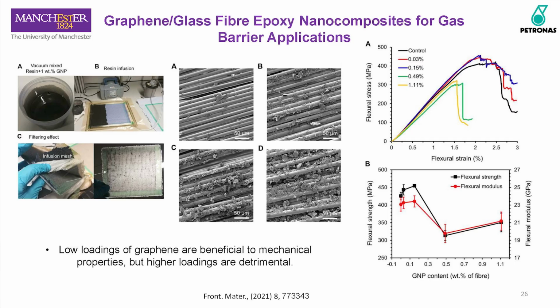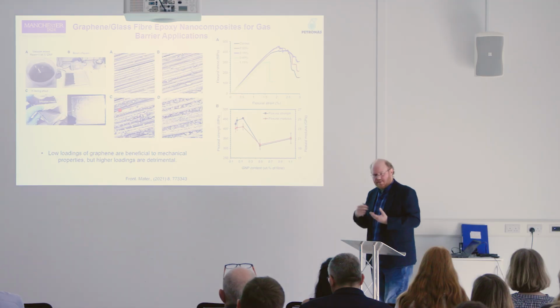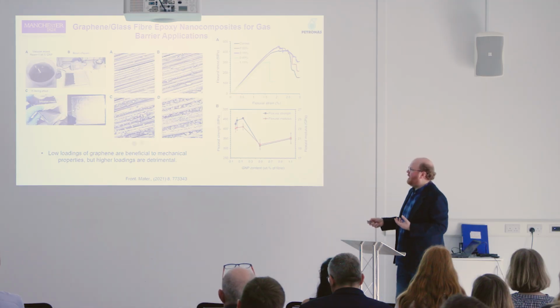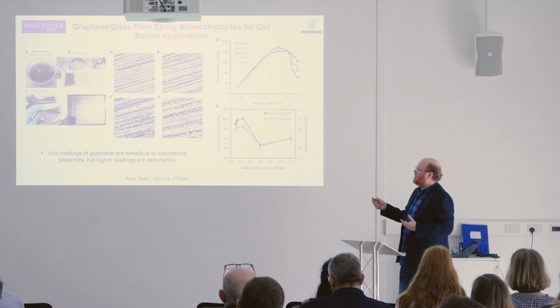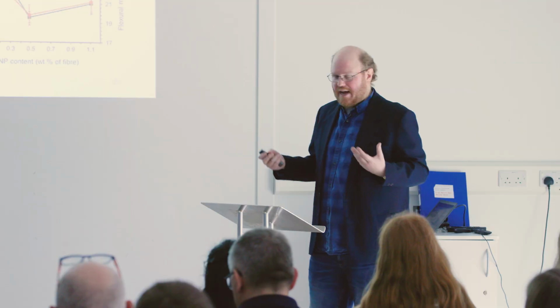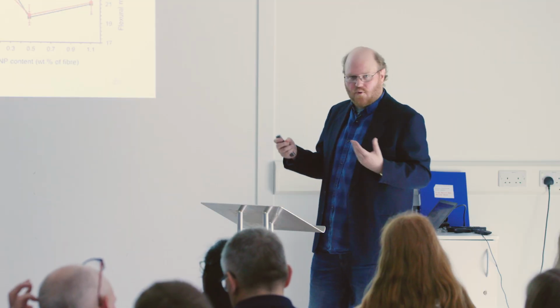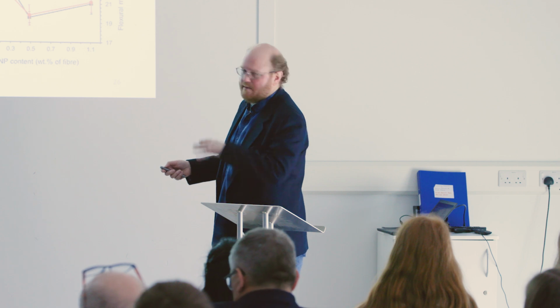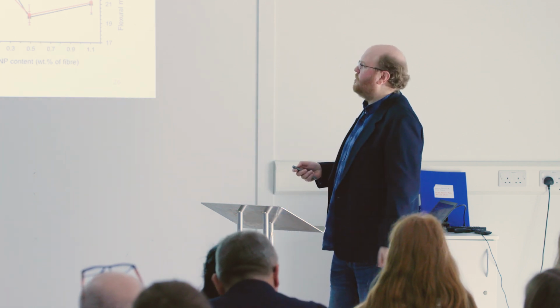This was looking at glass fiber, again, coating these. One of the challenges that came up initially is that a lot of glass fiber or even carbon fiber is done through a process called resin infusion, where you basically add your graphene into your resin and try and infuse it like this. The problem with that is that you actually filter it out. The fibers themselves block all of the graphene, so you don't get a really nice dispersion of your filler. In glass fiber, you can see that visually because you get your black on one side of it and a very poor dispersion.